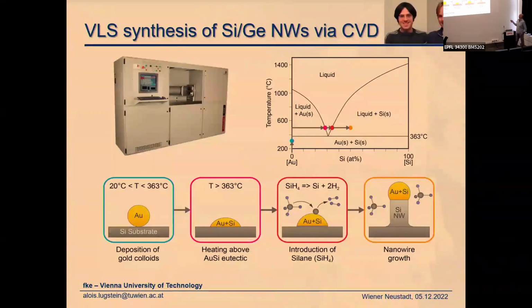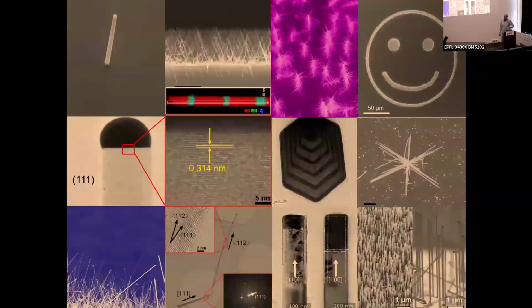Christoph Schöndorfer and Matthias Steinmeier were my first two PhD students, and they introduced the VLS mechanism, so the bottom-up growth of nanowires using a catalytic particle. We use gold, then you introduce the respective gas, for example, silane, and that is dissolved in the gold particle. It supersaturates the gold particle, then you grow a nanowire below this particle. So these are a few examples of the nanowires that we have grown.